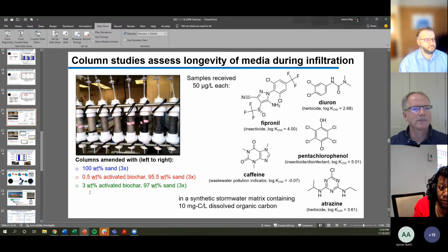So in terms of the pyrolysis and what else could come off of the biochar during application, what we did make sure to test is that we don't leach caffeine into the stormwater that we're trying to treat. I think that's a question that comes up a lot: you're using coffee grounds, so there must be caffeine around. The other nice thing about the activation step, where we added in the potassium hydroxide, which increased the surface area, is that it also helped release a lot of residual caffeine that was trapped inside of the biochars that we burned at much lower temperatures and without the chemical activations. That was another benefit of that step.